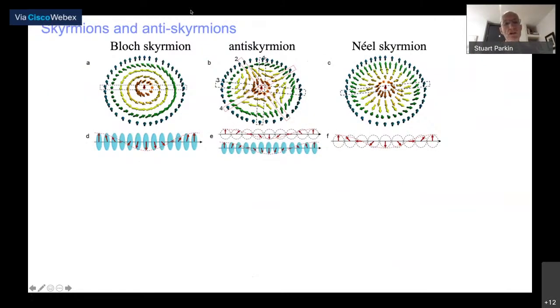So I want to just briefly then remind you or introduce to you the concept of a skyrmion and an anti-skyrmion. So it turns out then that if you have a material which is magnetized in one direction, let's say along this tetragonal axis, for some region of temperature and magnetic field, the magnetic moments are not oriented parallel to one another, but the ground state breaks up into an array of skyrmions or anti-skyrmions. Now, what is a skyrmion? Then it's basically a circular object in which the magnetization outside is oriented up, and in the middle it's oriented down. And the wall surrounding this object is chiral because of a volumetric Dzyaloshinskii-Moriya exchange interaction that wants the moments neither to be parallel, as in a ferromagnet, nor anti-parallel, as in an antiferromagnet, but it wants the moments to be perpendicular to each other in a vector direction, which defines a chirality.